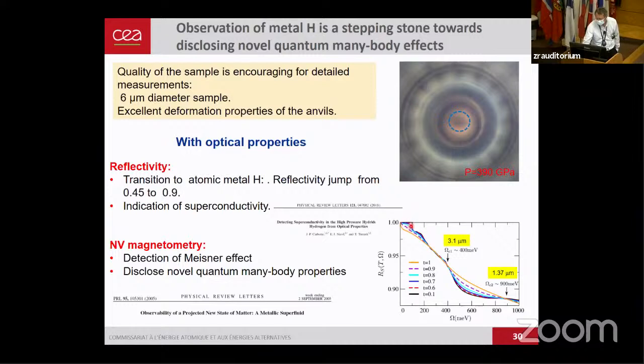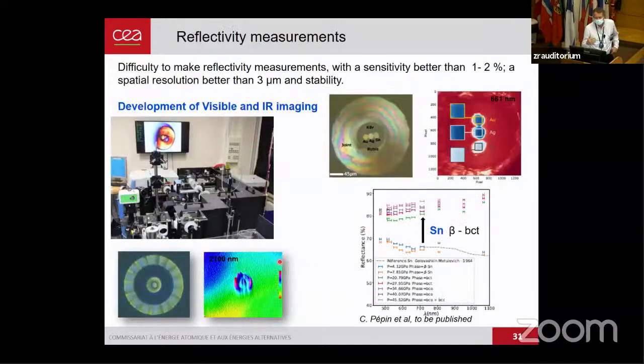If you do the reflectivity in the infrared, you can measure the superconducting gap, but not going so far in the far infrared, you can have an anomaly on the reflectivity around 1 to 3 microns. This reflectivity anomaly, if measured, could probably be taken as an indication of superconductivity. Then you can also do NV magnetometry to disclose the Meissner effect of the superconductivity. These are measurements that we are pushing and developing. This is not synchrotron measurements, but lab measurements.